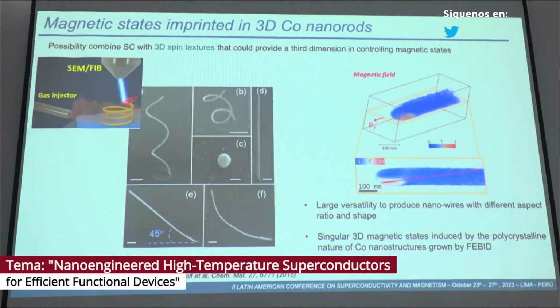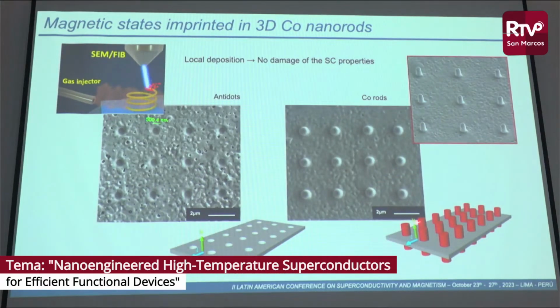Also, in a more complicated structure, in this case, what we use is a ferromagnet, which was a 3D ferromagnet, in this case a rod, which was grown with a particular texture, like a nanorod. And here, for example, what we did is in a YBCO layer, we fabricated different dots in the layer, and inside of the dots, we put several nanorods. And these nanorods have a particular 3D magnetic structure, vortices inside the nanorods, and we try to move or to control the magnetization of the nanorods with the superconductor.